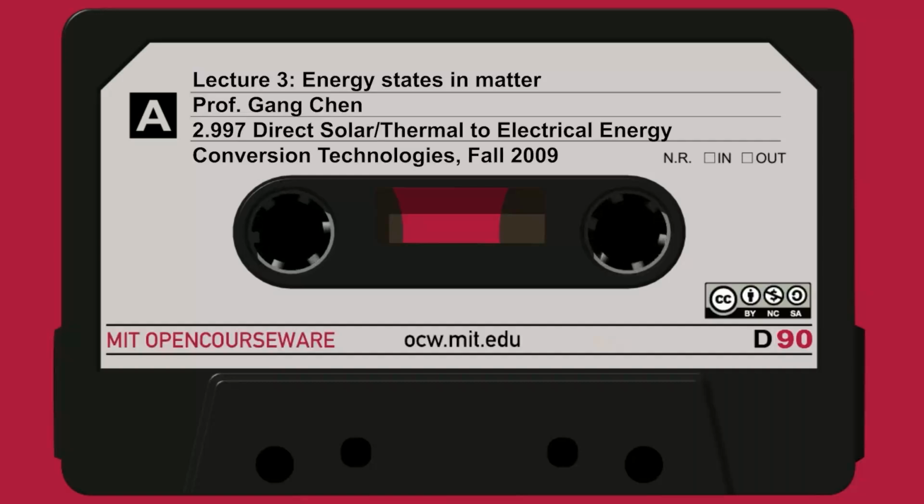The reason is that in a gallium arsenide device, a microelectronic device, you inject the electron here, you inject the hole. That's by device design. You put in a current, you actually inject into the material, and then the electron falls to the bottom and recombines between here and here, giving off a photon. It's much easier to do that in a direct gap because there's null wave vector mismatch, and here it's very difficult for the electron to recombine with the hole.